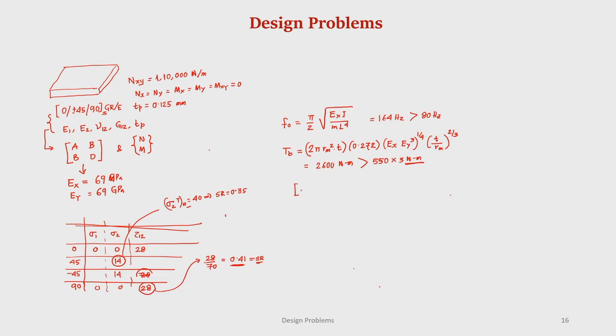Now, we can say that this 0 plus minus 45 90 symmetric graphite epoxy is a feasible solution, which actually reduces the weight. You can now try to see what the weight saving is. Like the earlier case, we can also find out the weight savings here, but what we have seen is that this is far stronger than required. So, maybe we can try with glass epoxy and do the same exercise, and then take a decision whether we should go for glass epoxy or graphite epoxy, because the cost of glass epoxy will be much less compared to that of graphite epoxy.